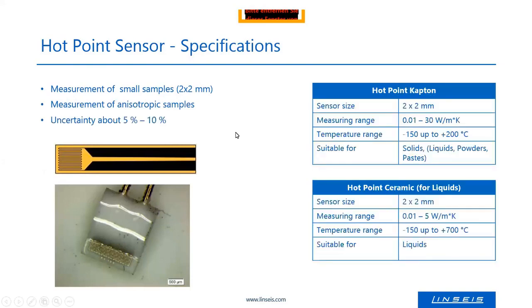The specifications of the hot point sensor: it was designed mainly for small samples, down to 2 by 2 millimeter. It can be used also for anisotropic samples, which is quite useful. The uncertainty is between 5 and 10%, and the measurement range of the Kapton hot point is between 0.01 and 30 watt per meter Kelvin. And for the ceramic hot point, it's 0.01 up to 5 watt per meter Kelvin.